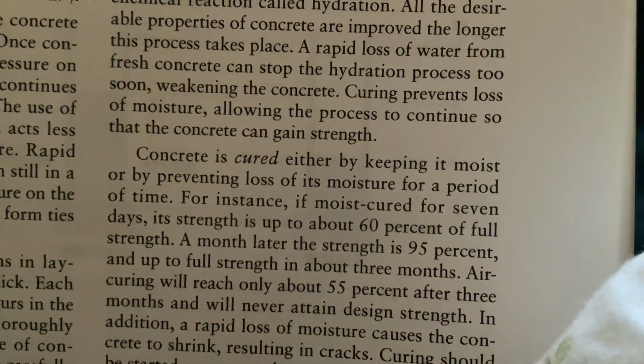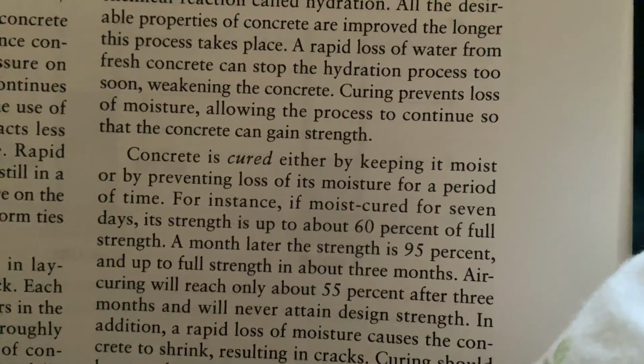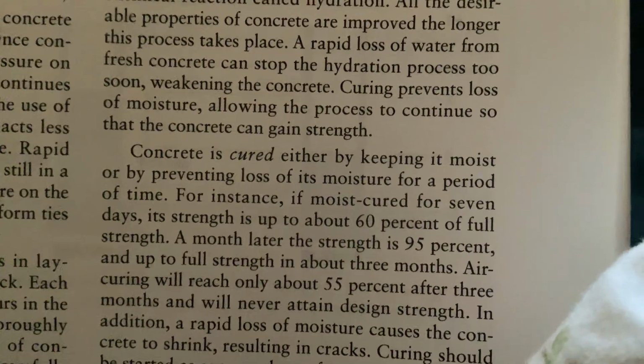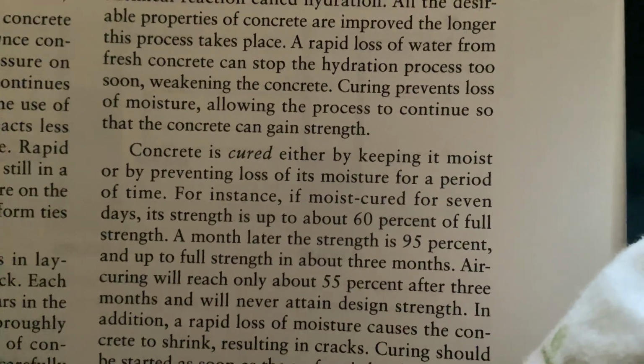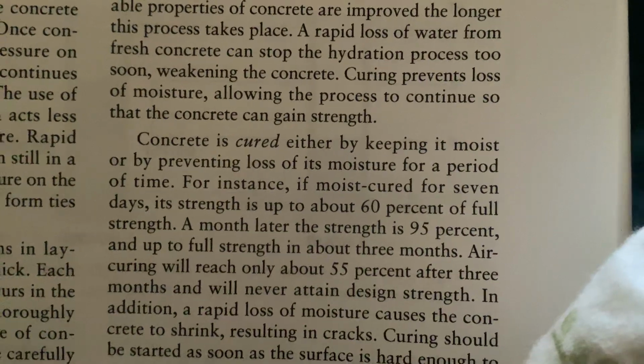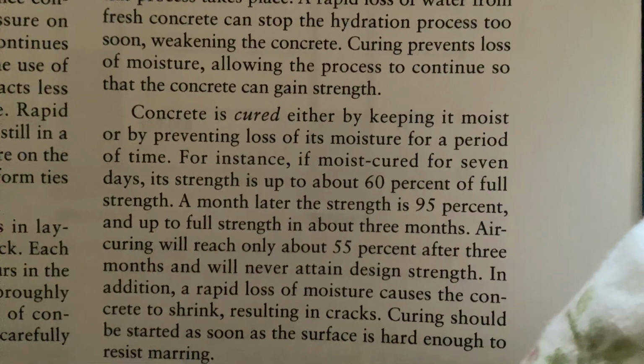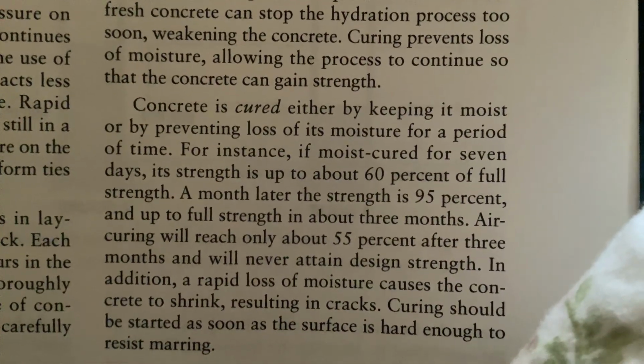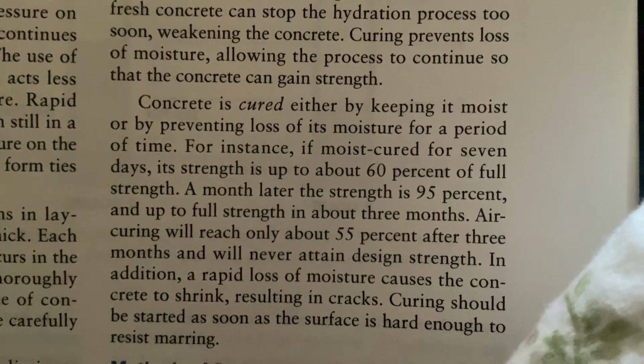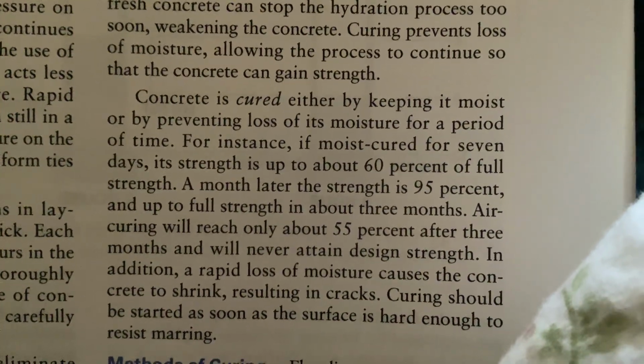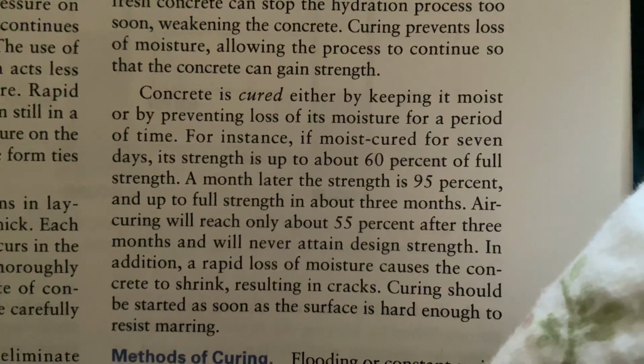Concrete is cured either by keeping it moist or preventing loss of moisture for a period of time. For instance, if moist cured for 7 days, its strength is up to 60% of full strength. A month later, the strength is 95% and up to full strength in about 3 months. Air curing will reach only 55% after 3 months and will never attain design strength.